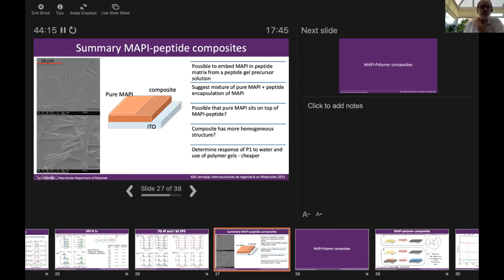We're not entirely sure what the differences are here, because usually pure MAPI you see as quite granular structures in the SEM, whereas obviously we're seeing this more fibrous structure. When you add in the peptide, the whole surface becomes more homogeneous. So the peptide perovskite composite appears to be more homogeneous, and maybe this is also helping lead to the improved stability of the material. So it may be that these lines we're seeing here are actually the pure MAPI, and then this flatter material is the encapsulated MAPI.